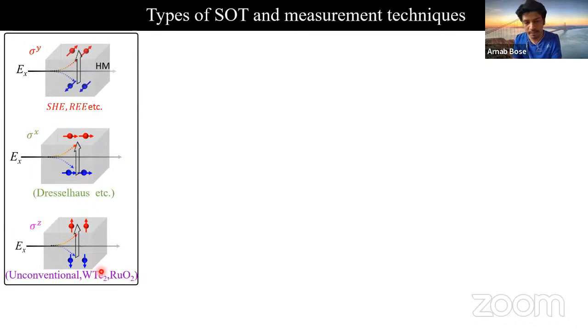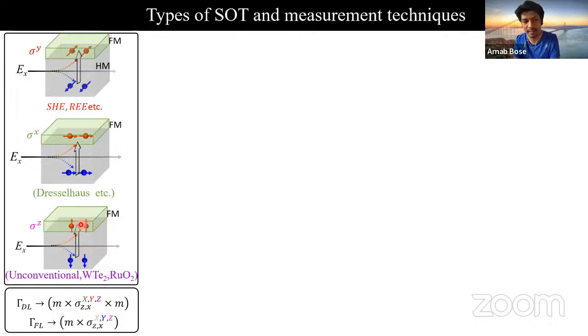In some materials where we have lower symmetry, sometimes that can also allow us to have out-of-plane spins flowing in the out-of-plane direction. Now, when we have spin current, they will interact with the adjacent magnet, and it can produce 6 different types of torques, 3 different types of damping-like torques, and 3 different types of field-like torques. These torques are very useful to manipulate the magnetization state and vice versa. Meaning, if we know the spin torque response in a system, from that we can know what type of spin current is generated. So that would be very useful.